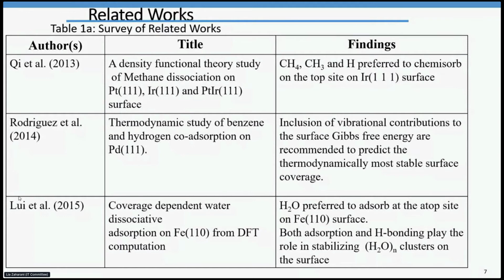Lui et al. 2015 work titled Coverage-Dependent Water Dissociative Adsorption on Iron 110 from DFT Computation. Water preferred adsorption on the atop site on the iron surface. Both adsorption and hydrogen bonding play the role in the stabilization of the water cluster on the surface.